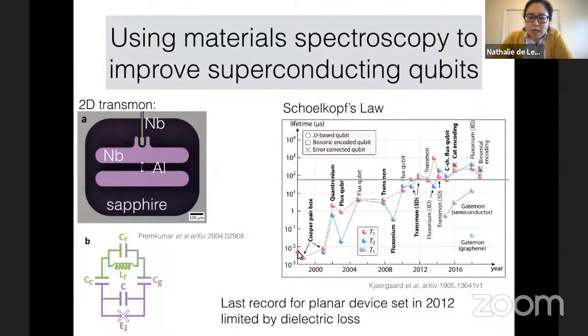And there was a lot of steady improvement in the coherence time of planar transmons for a long time, from the late 90s up until about 2012. There was this steady march of improving these systems. But one thing that people don't mention as much is that the last time somebody set a record for a planar device was about 2012. So all of the improvements since then have been things like 3D cavities that can have much longer lifetimes, but the qubit coherence times are kind of stuck at around 100 microseconds, despite enormous effort around the world.